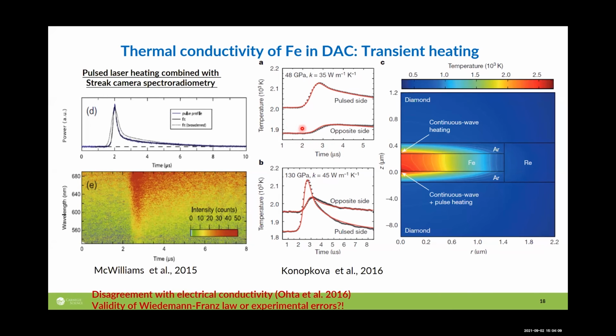So you are kind of here, and then you send in a single laser pulse from one side, and the temperature on this heated side increases fast, and then a thermal wave propagates across the sample and reaches the other side with this kind of delay. By performing thermal finite element calculations, you determine the thermal conductivity. The temperature here is measured by spectroradiometry using a streak camera, and this is an example of that kind of measurement. It seems to be a clean experiment to do, but in reality, laser heating experiments are quite messy and difficult.